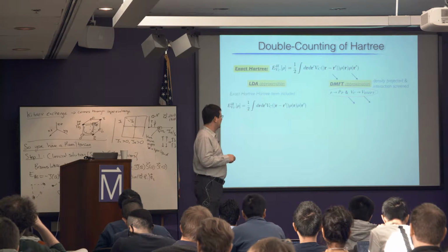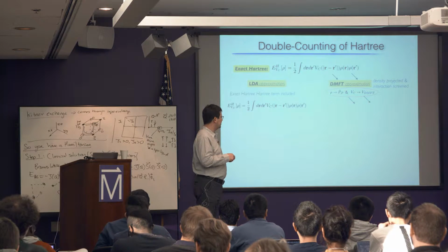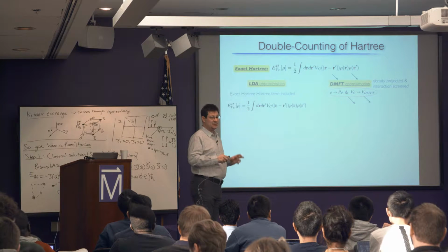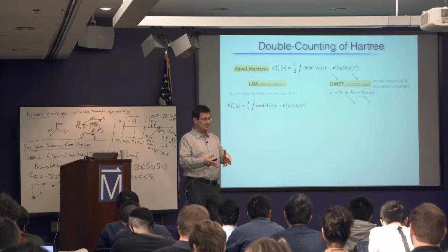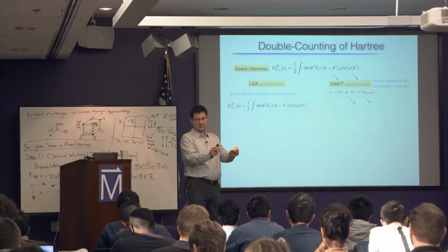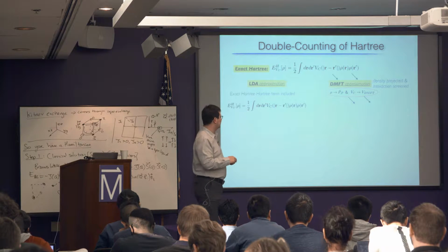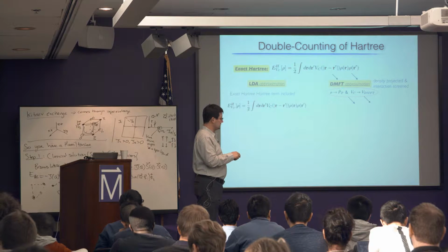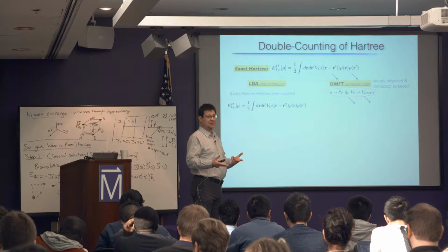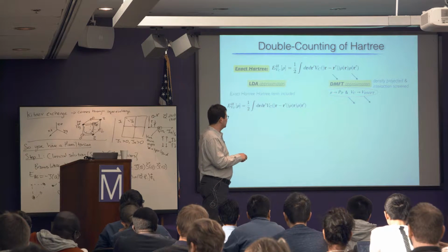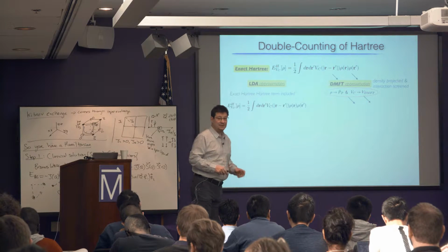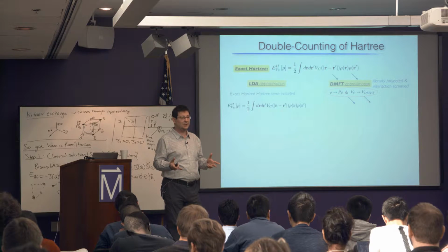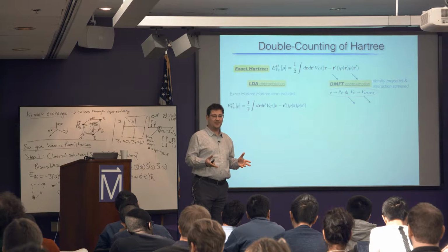So what do we do? Well, we take our charge density rho, and we project it. This projection, I showed you yesterday how it works. Basically, you just insert twice your functions, phi, whatever they are. But here I'm just writing this as a P on rho, which means projection. I go from the entire charge density to the local charge density. And then at the same time, I need to screen the Coulomb repulsion. Now, why do I need to screen the Coulomb repulsion?